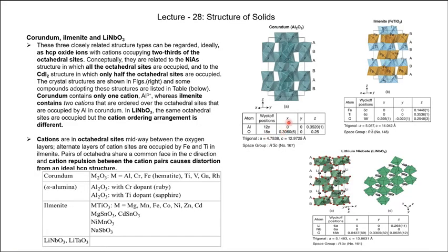And then if we go to the Wyckoff position, we can see the atomic positional system called fractional coordinates: 0, 0, and 0.35 for aluminium, and that is 0.306, 0 and 0.25 for oxygen. There are some special positions, as well as general positions too. Okay, so